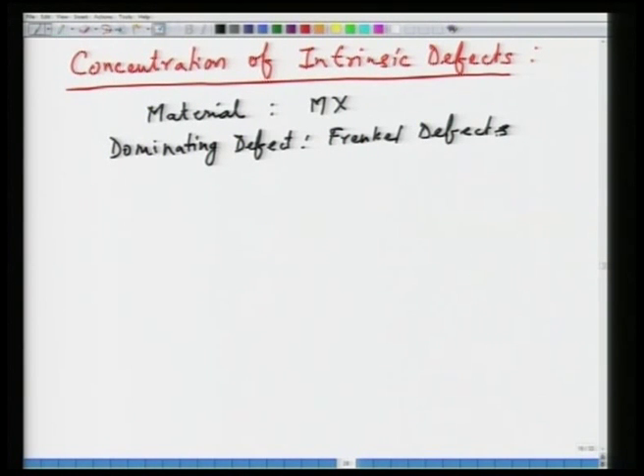So if it was a Frenkel defect, then I can write this as MM plus XX as MI plus VM plus XX. So you have site balance because you have one anion site and one cation site. You have charge valence. The interstitial carrying two charges is balanced by two negative charges on the metal vacancy site. So this is your defect reaction.